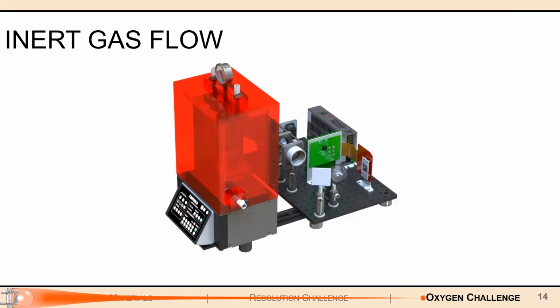So essentially, our printing chamber here is hooked up to a tank of some sort of inert gas, namely nitrogen or argon. And then as you're printing through, you basically flush the atmosphere with a flow of inert gas. What that does is that the inert gas will displace the oxygen from the atmosphere and in the resin and prevent it from interfering with their catalytic cycle. And that allows your polymerizations to go to completion and for prints to look a lot more high in resolution.